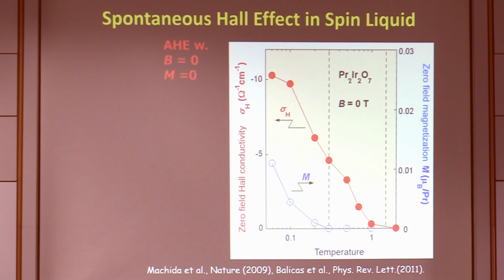This is the material of the pyrochlore oxide class, an iridium oxide, so the conduction electrons come from 5d bands. When we cool down the system, it is a spin liquid, and this measurement was done at dilution refrigerator temperatures, below a few Kelvin.